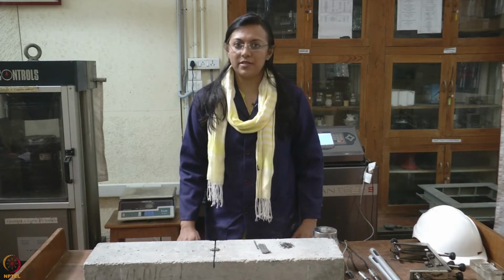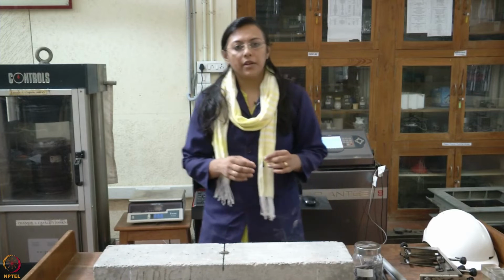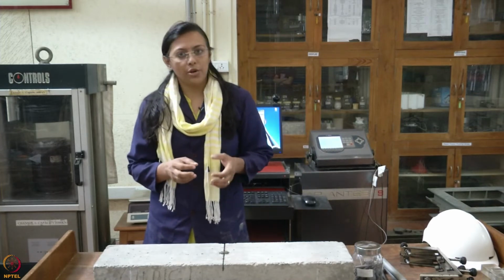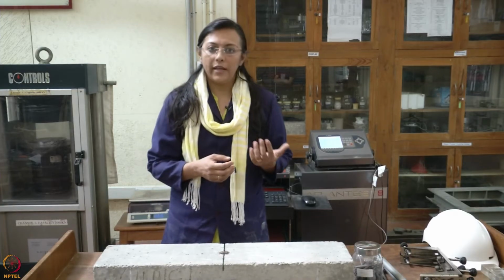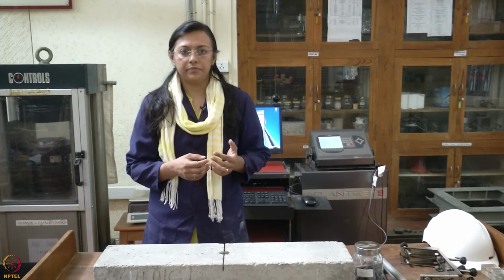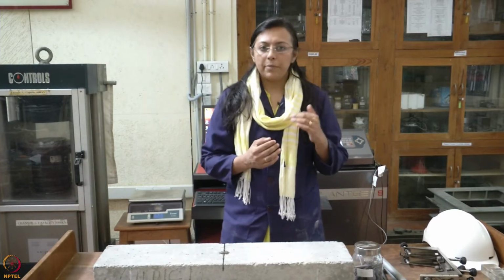So, first of all, the main disadvantage of using plain concrete is its brittle failure. The advantage of fiber reinforced concrete over plain concrete is its enhanced ductility, post-crack load carrying capacity, etc. This post-crack load carrying capacity is captured by the post-peak response, which can be derived from this test of flexural toughness characterization. The objective of this test is to measure the effectiveness of fibers and to obtain a post-peak response.